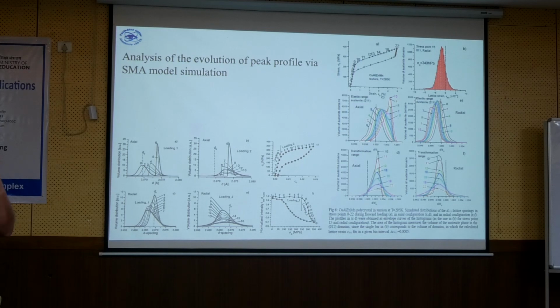Why? If you think about it, it's very clear. In the material, there is some limit for local stress, and when you arrive at this limit, which is the Martensitic transformation, if the Martensitic transformation in 2 grains fills this limit, it will start to transform, and the stress goes down. And then in the other part here from 6 to 10, the intensity goes down.